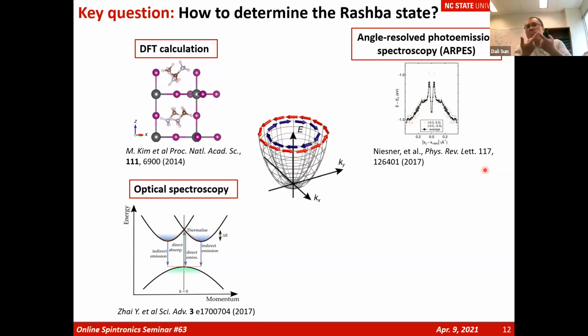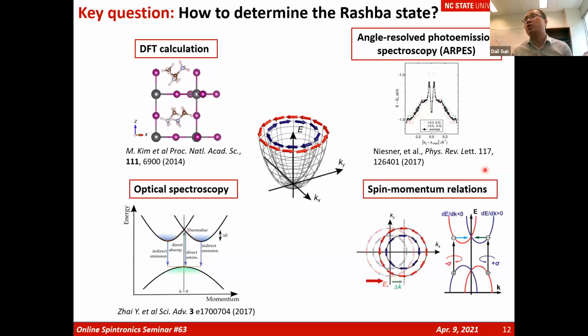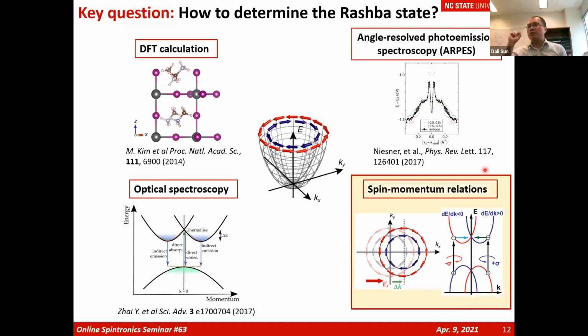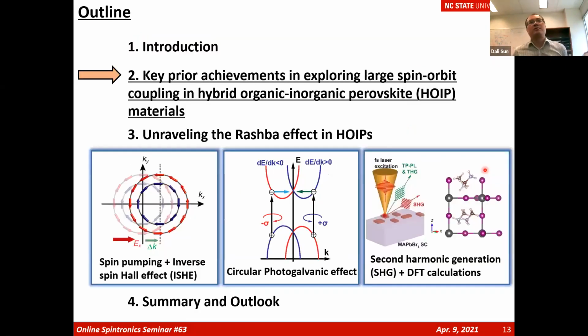But still, this method didn't tell you the spin momentum correlations. It means just a large delta E, which gives you the splitting of energy, but not the momentum. So we believe the best way to address the Rashba effect in any materials, actually in the hybrid perovskite material, should be to adjust the spin momentum relations by using spin pumping or circular photogalvanic effect. So that's basically the motivation of our work to examine the Rashba effect in the MAPbBr3 single crystals.